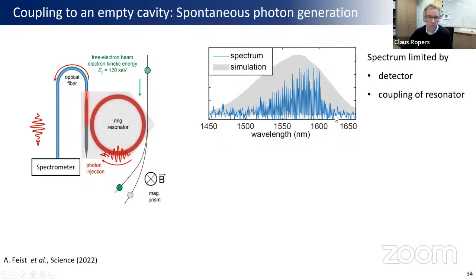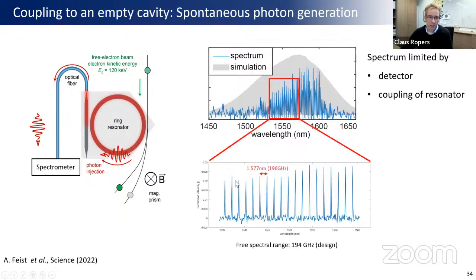This is the optical spectrum that we can measure with an optical spectrometer at the output here. If we do this with a little bit better spectral resolution in the spectrometer, we actually see that what we produce here by a single electron, or by a large ensemble of single electrons, is the longitudinal cavity modes of a particular mode family, the mode family which couples to, or which corresponds to this longitudinal field, which is phase matched. Yeah? So we have individual resonances here, optical resonances that we populate, and the spacing corresponds to the free spectral range of this resonator. Okay, it's limited on both sides by the detector efficiency and also by the phase matching condition.